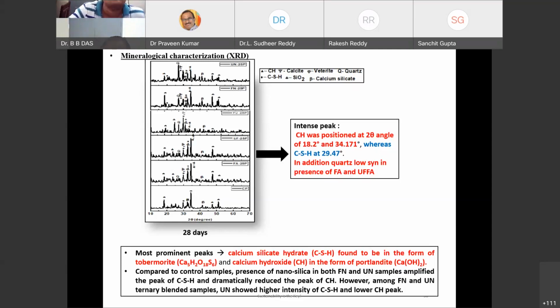Now, what are these additional peaks, or the prominent peaks? These prominent peaks are calcium silicate hydrate, found in the form of tobermorite, and calcium hydroxide in the form of portlandite. So, what is happening actually? Presence of nanosilica in both fly ash nanoparticle and ultrafine fly ash nanoparticle samples amplifies the peak of CSH and dramatically reduces the peak of CH. However, among the FN and UN samples, UN showed a higher intensity of CSH and lower CH. That is fine. But remember, the moment I go to nanoparticles, the tobermorite peak, that is basically your gel, okay, that is basically your gel, is found to be very much intensified.